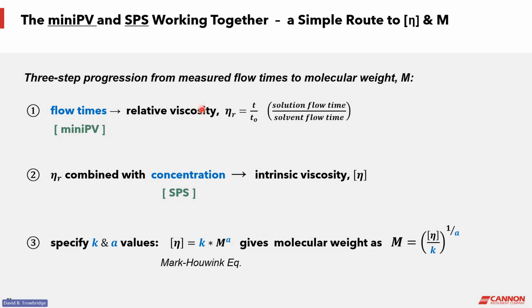It gives us the flow times for the solvent and for the solution, and allows us to calculate the relative viscosity. And actually, it is simply reduced to the ratio of the flow times. You don't even really have to calculate the viscosities from the flow times. In many cases, just the flow times themselves give you a simple ratio that'll give you the relative viscosity. Then you can combine that relative viscosity with the concentration, which is the contribution from the SPS. That allows us to get derived viscosities and, most significantly, the intrinsic viscosity.